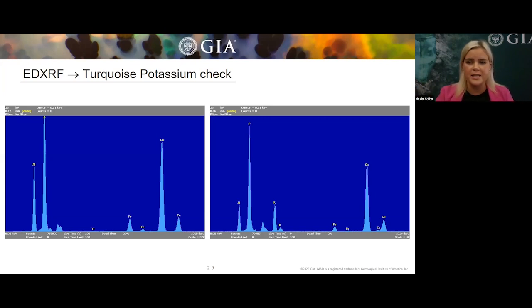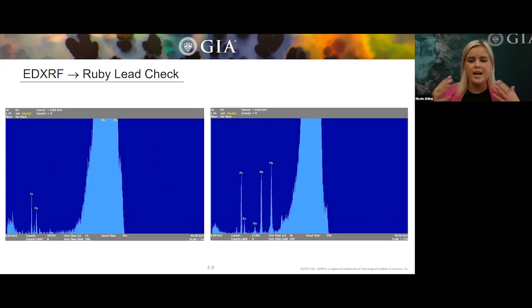So again, no potassium, potassium. And the same thing is kind of what's going to look like for a lead glass filled ruby as well. So on the left-hand side of the screen, you see ruby was ran, you only got your copper and you only got your iron was found. And then on the other graph, you see that actually very, very high levels of lead, again, indicated by its symbol Pb. So this ruby, again, with additional confirmation, so maybe gas bubbles, filled veins, with this XRF showing proof of lead being present, this ruby will now be probably sent out as a manufactured product consisting of your ruby and your lead glass.